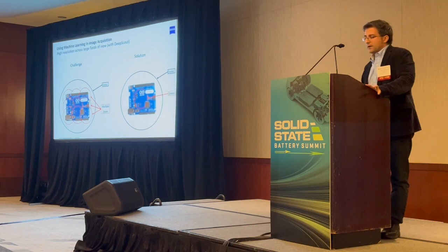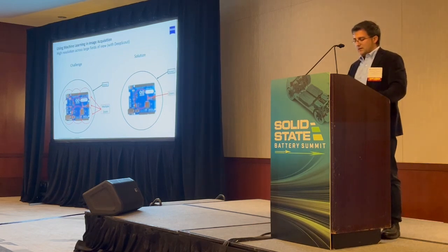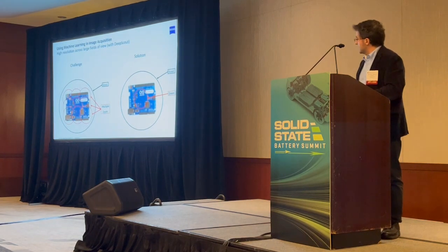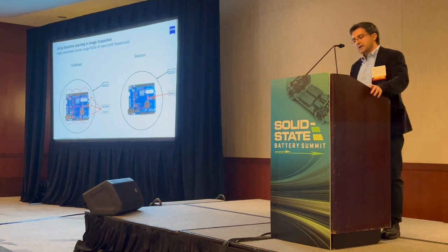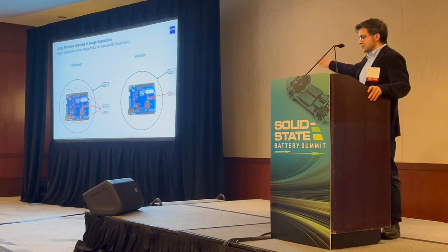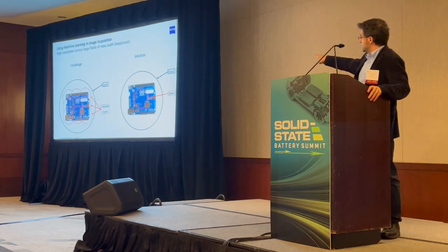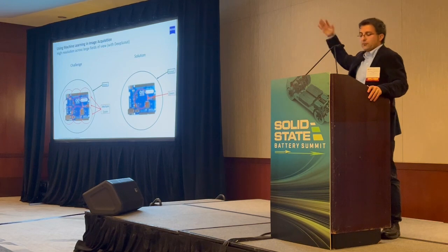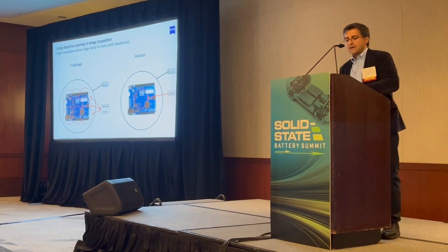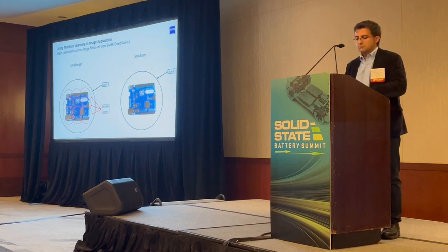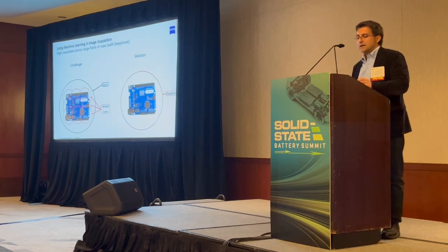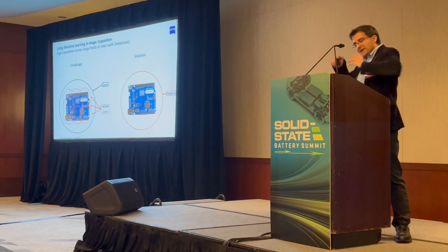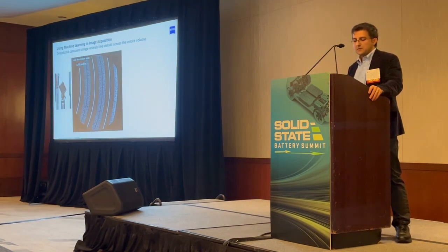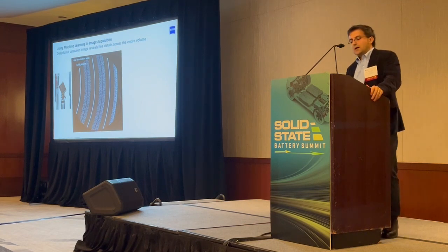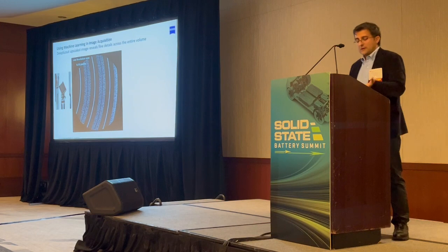What if we use a deep learning network to train on the data from a small region of interest at high resolution, take a low resolution scan of the full sample, large field of view, and now expand that learning network to the full sample. And thus, we are calling it now DeepScout. So with DeepScout, it is possible to recover resolution details across a large field of view. And that's the innovation of this second part of the deep learning algorithms for pre-reconstruction or for the reconstruction process.